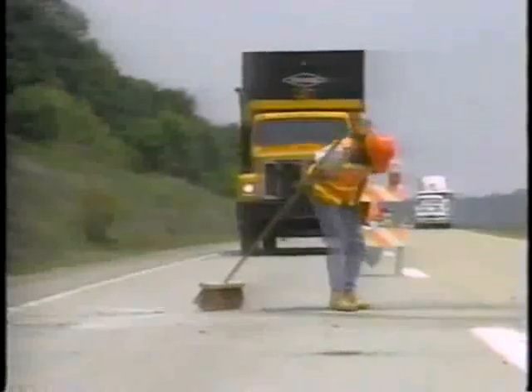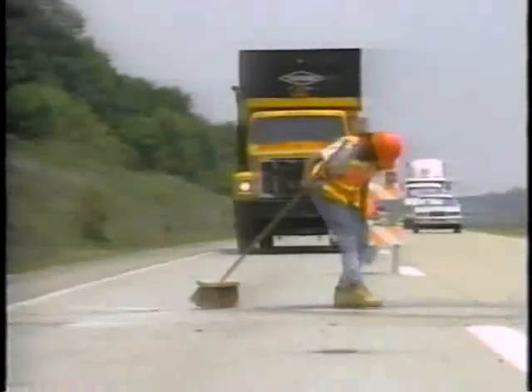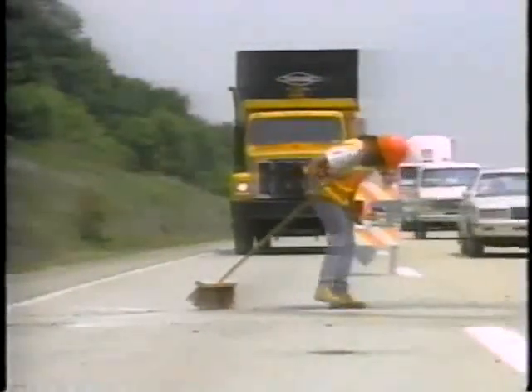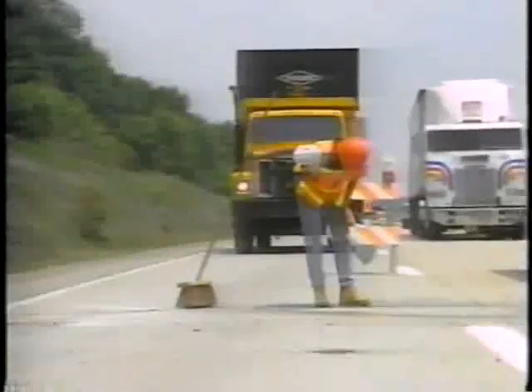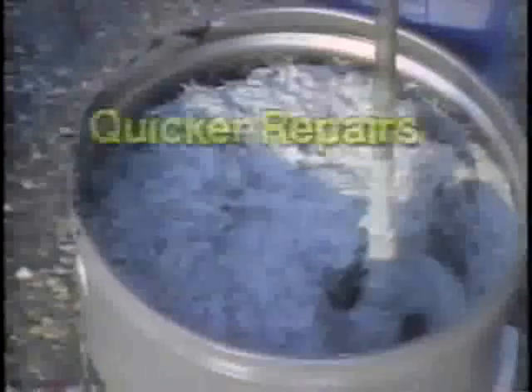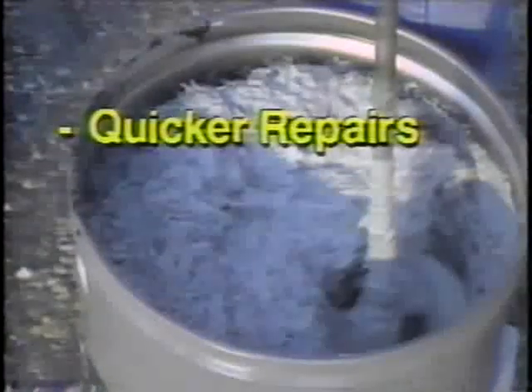Fewer than 2% of the installed patches have failed. However, some cementitious products have developed hairline shrinkage cracks in large patches. Type 3 cement with accelerators can provide rapid setting repairs at costs lower than those of proprietary materials. In the end, we will answer questions such as, are quicker, less labor-intensive methods possible with these innovative materials?